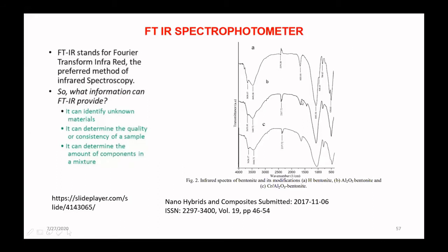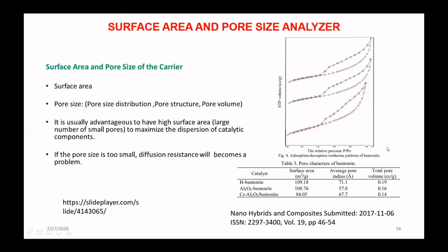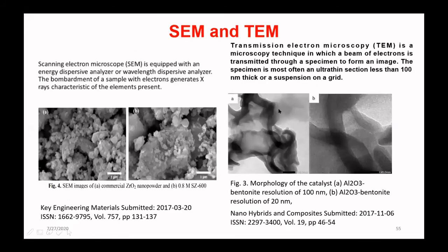At the top of this figure, we can see the infrared spectra of the H-bentonite, B is alumina bentonite, and chrome. The most important thing is there is no damage in the silica structure. That means the structure is still good. The layer still exists, and it's relevant with the other analyses, for example TEM, and also the XRD of these materials.